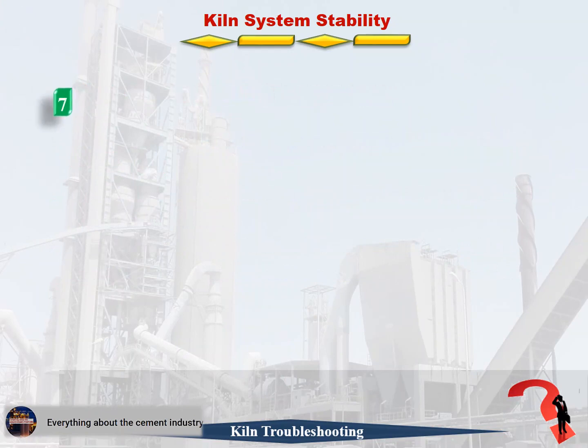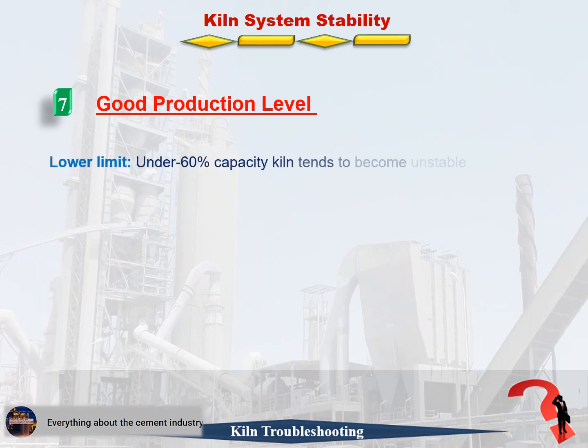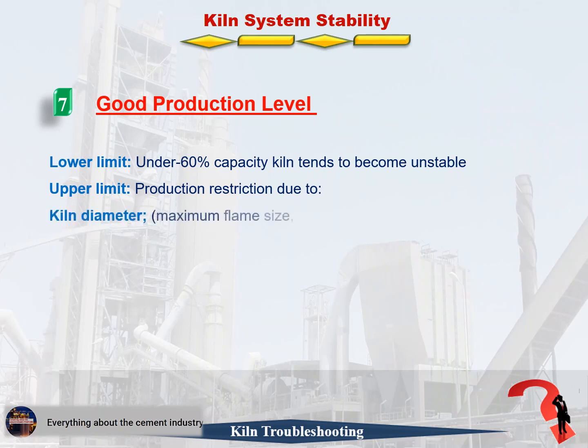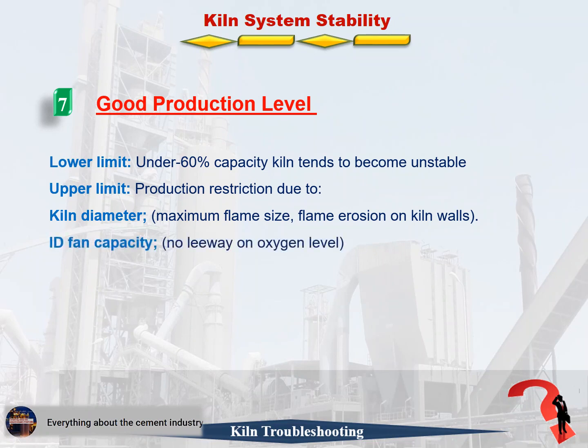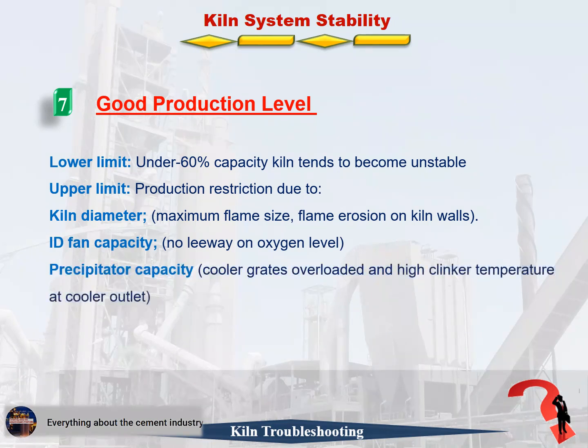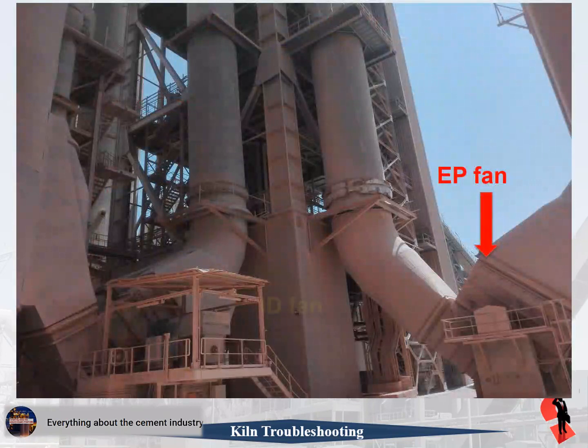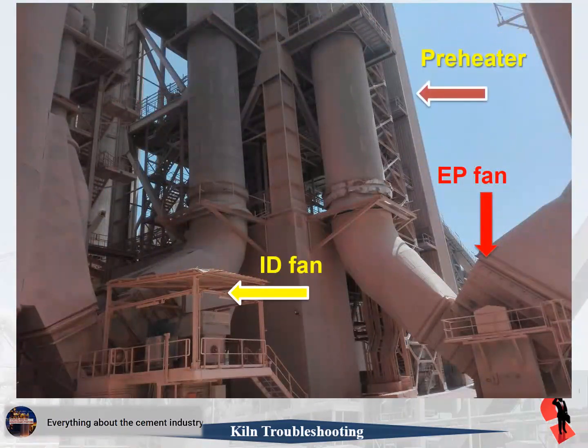7. Good production level. Firstly, lower limit: under 60% capacity the kiln tends to become unstable. Secondly, upper limit: production restriction due to 1. Kiln diameter, maximum flame size, flame erosion on kiln walls. 2. ID fan capacity, no leeway on oxygen level. 3. Precipitator capacity, cooler grates overloaded and high clinker temperature at cooler outlet. This picture shows the ID fan, preheater.